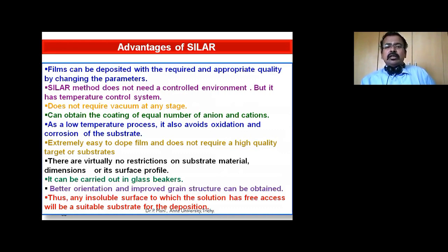And this method doesn't need a controlled environment, but it has a temperature controlled system. It doesn't require vacuum at any stage. It's a simple one. We can obtain the coating of equal number of anions and cations in a low temperature process. It also avoids oxidation and corrosion of the substrate. It is extremely easy to dope the film and doesn't require a high quality target or substrates. There are no restrictions on substrate materials, dimensions, and surface profiles. It can be carried out in glass beakers simply. Better orientation and improved grain structure can be obtained from this method. Thus, any insoluble surface to which the solution has free access will be a suitable substrate for the deposition.